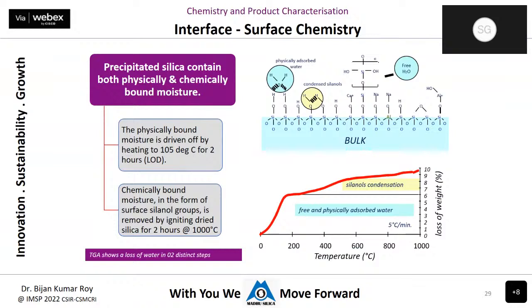Now, the interface. The silica structure is being formed, but since its surface is surrounded by different functional groups, the interface chemistry is very important for silica and its performance in rubber compounds. As we know, silica has two kinds of moisture. One is physically bound moisture that can be driven off by heating at 105 degrees centigrade for 2 hours. We call it loss on drying. And chemically bound moisture in the form of surface silanol groups, the hydroxyl groups, that cannot be driven off at 105 degrees centigrade. That can only be removed by heating silica at 1000 degrees centigrade for 2 hours.